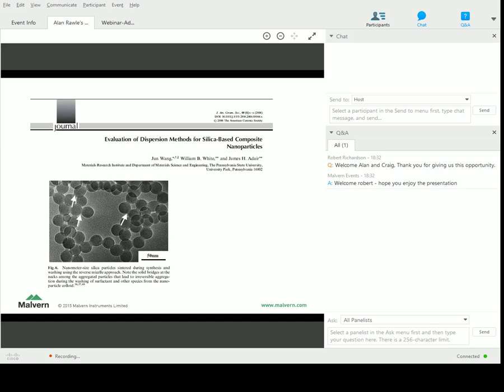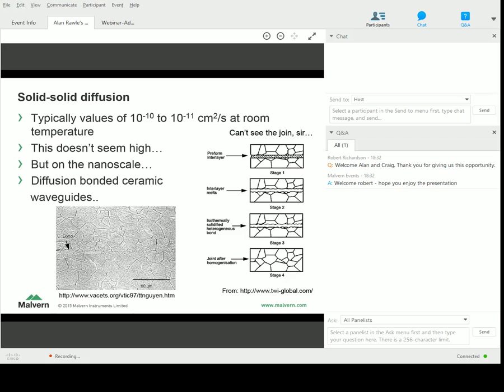I've done that with copper powders, by the way, small copper powders with nitric acid, and what took 60 minutes with ultrasound could be accomplished in about 10 seconds with that particular form of dispersion. So solid-solid diffusion is actually used in diffusion bonded ceramic waveguides, something that I've got experience of many years ago at the Royal Signals and Radar Establishment, where you could make high-powered CO2 lasers, because what you'd want is maybe